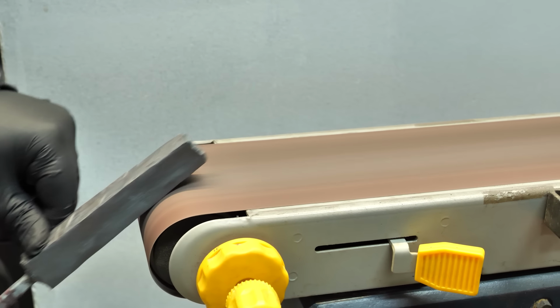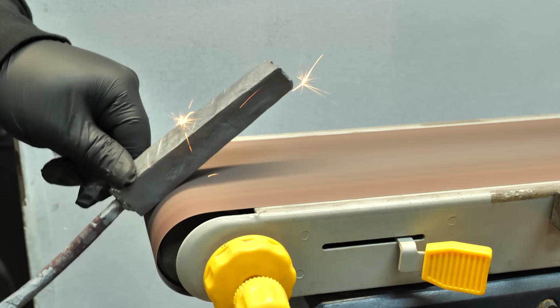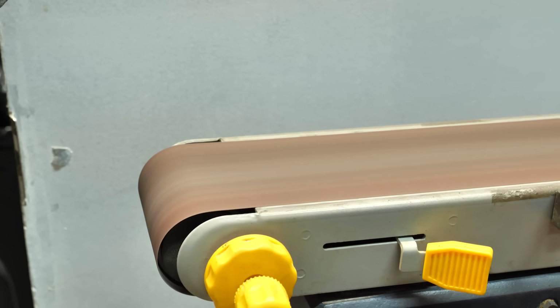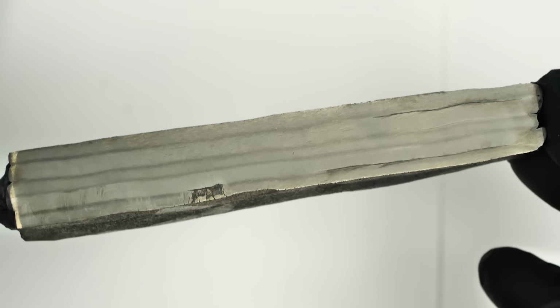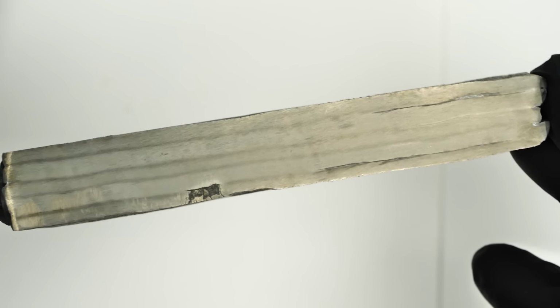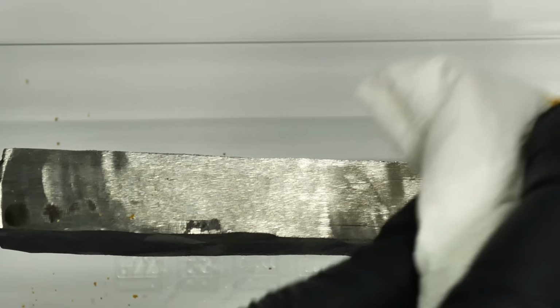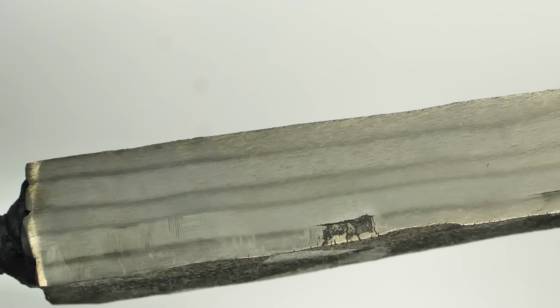Since this is my first time doing this, I wanted to make sure the weld was good, so I let the billet cool off and ground through one side. And sure enough, it was a nice clean join for the most part. While it was cold, I figured it would be nice to do a quick test etch so you can see the layers. A little bit of ferric chloride was all it took, and sure enough, we see distinct layers.